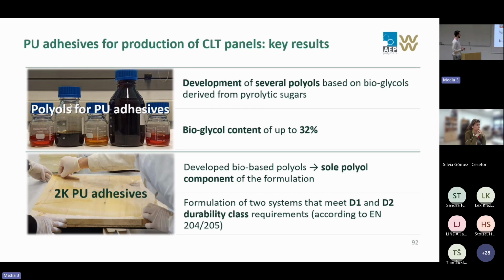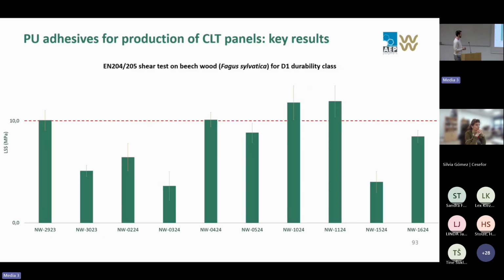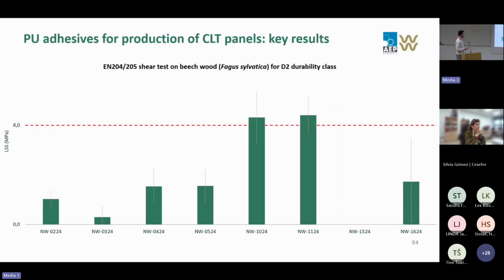We managed to obtain two systems that meet the criteria for D1 and D2 durability class requirements according to the specified standard. Here you can see a summary of some of the systems that were developed. This is the threshold for the D1 durability class, and these two polyols clearly surpass the threshold. The same two polyols also are eligible to be considered D2 durability class adhesives, as they also managed to pass the required threshold for this durability class.